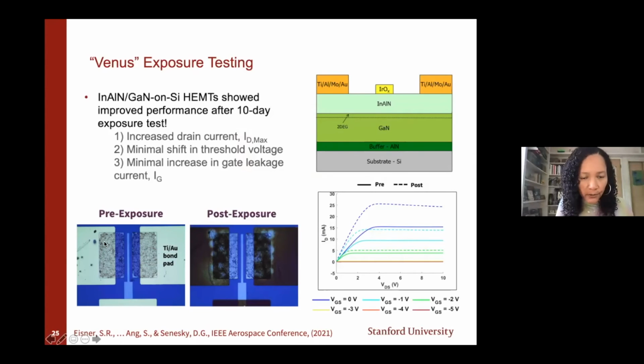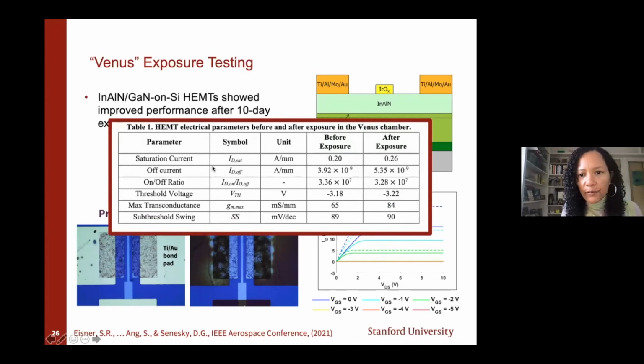Okay, so in our first test, this is a pre-exposure. This is a more recent version of our gallium nitride HEMT. We have our bond pads here, our titanium, aluminum, molybdenum, gold ohmic contact, and then our Schottky contact. We've been looking at iridium oxide, these metal oxides, which have high thermal stability, as our gate material. So pre-Venus exposure and then post-Venus, we see these oxidation effects occurring. But if you look at the IV response, pre and post, it's really interesting. I think I added a table just to summarize. We find that there's a slight increase in the saturation current.